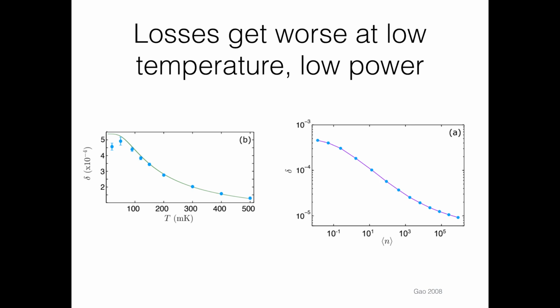So this is fundamentally weird, because if I gave you a crystal of something and I said, how lossy is this thing at green wavelengths or something like that, you'd shine a laser at it, you would look at the attenuation on the other side, you'd do a Beer's law calculation, and you wouldn't really sweat the power of the laser too much, right? If it fluctuates by a factor of a few, you're still gonna get the same number at the end of the day. So here, what this says is that the losses, the number that I would get actually depends a lot on the power of the laser.